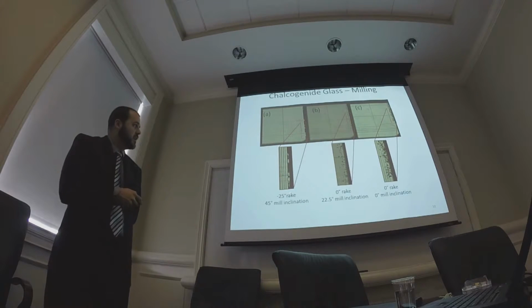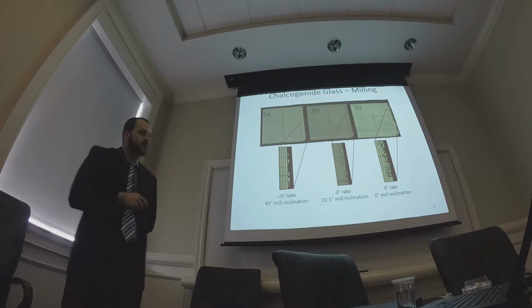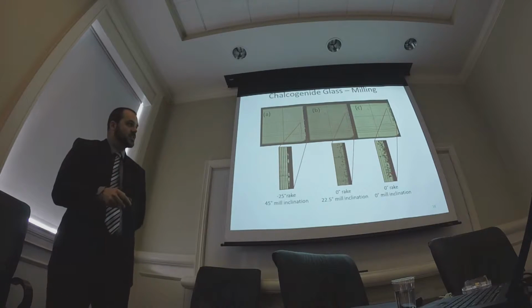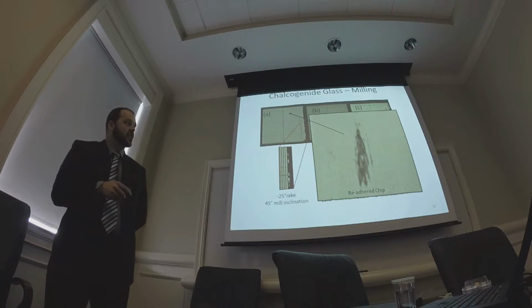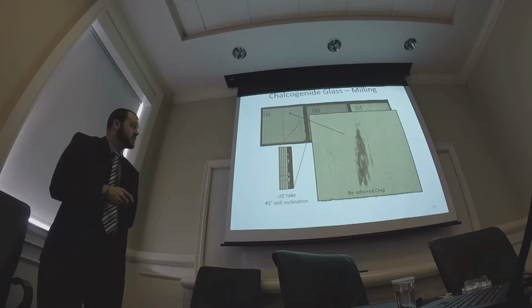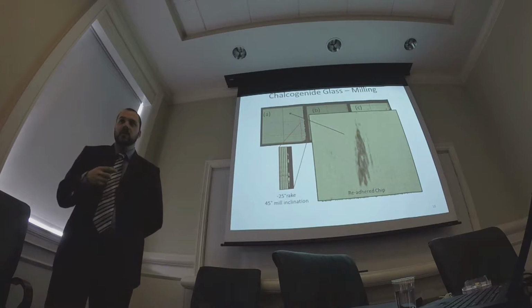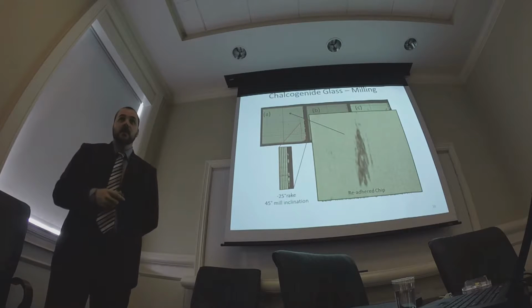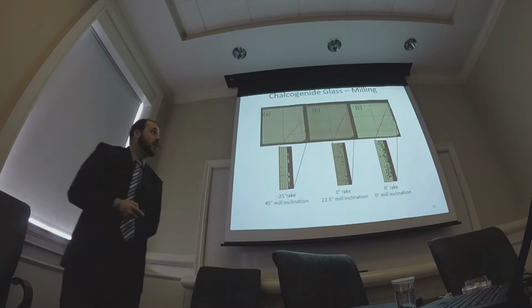So we saw negative rake tool had the least amount of fracture, and the zero rake tool with zero milling inclination had the most fracture, but this surface here showed re-adhered chips. So it appears that with the negative rake, we're sort of smearing the chip in front of it back into the surface. So this is not desirable.